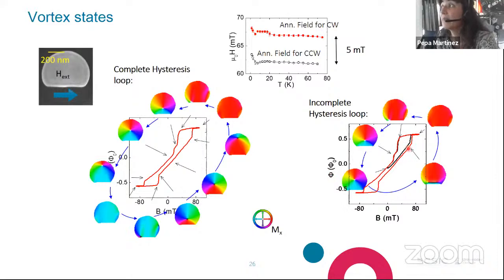How? Since the annihilation field of the vortex depends on if you have a counterclockwise or a clockwise vortex. Okay, this can be seen in this figure when we compare a complete hysteresis loop in red, where the vortex that is being annihilated here comes from a counterclockwise vortex, whereas in the black curve, the vortex that is being annihilated here comes from a clockwise circulating vortex. As you can see, there is a measurable difference between these two ones, thanks to the high sensitivity of these devices, okay, that allows us to verify the circulation of our vortices.